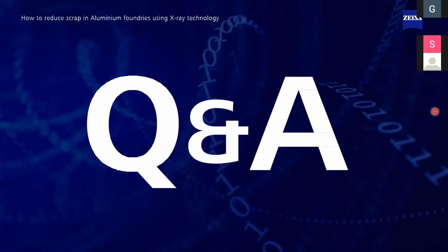in aluminum casting, cylinder block and cylinder head, they could get ROI in 8 months' time, because earlier, using a 2D machine, they were taking wrong decisions, and by using 3D, the same part which got rejected is now getting accepted because it is not at all hindering their next production phase. So on these kinds of crucial decisions, Volume-X could help, and ROI seems to be somewhere between 8 months and 1 year. And as I said, this technology started about 6 years ago, and we have already installed about 60 machines globally. And year on year, the numbers are increasing, which means all the customers are seeing the benefits, and then they are investing in these machines.